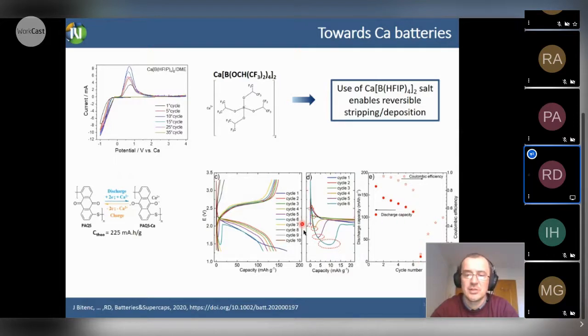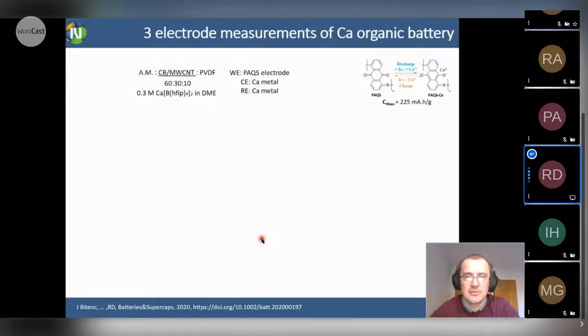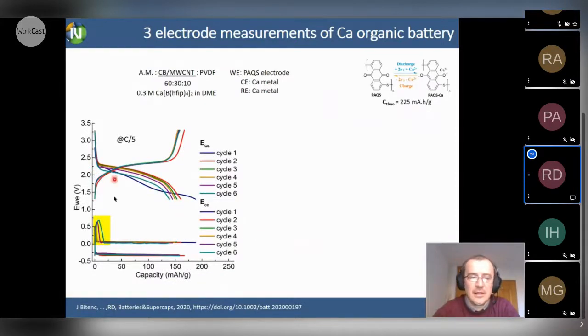And this capacity drop, if we magnify this part of the electrochemical curve, we see an increase of polarization from cycle to cycle, and after 7 cycles, the increase of polarization is so high that it actually hits the cutoff voltage, and that's why we have this sudden drop of the capacity. For that reason, we established 3 electrode measurements of the calcium organic battery in this particular system, and in that case we can distinguish between the cathode and the anode.